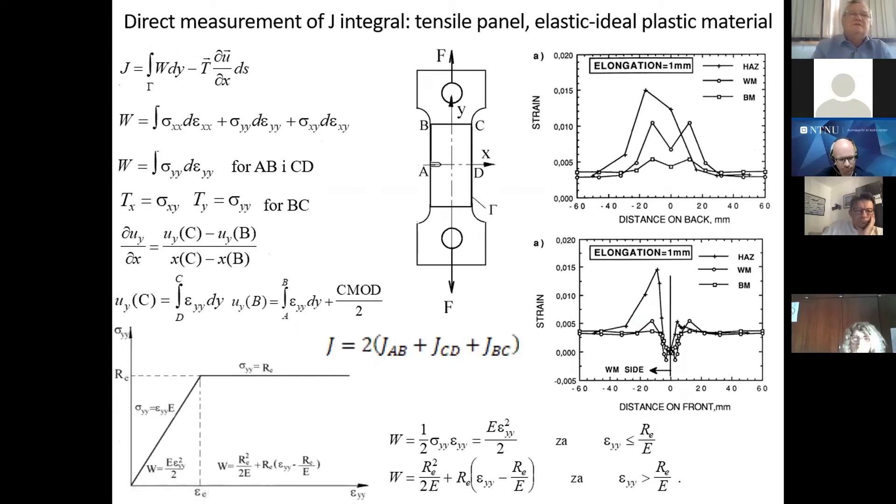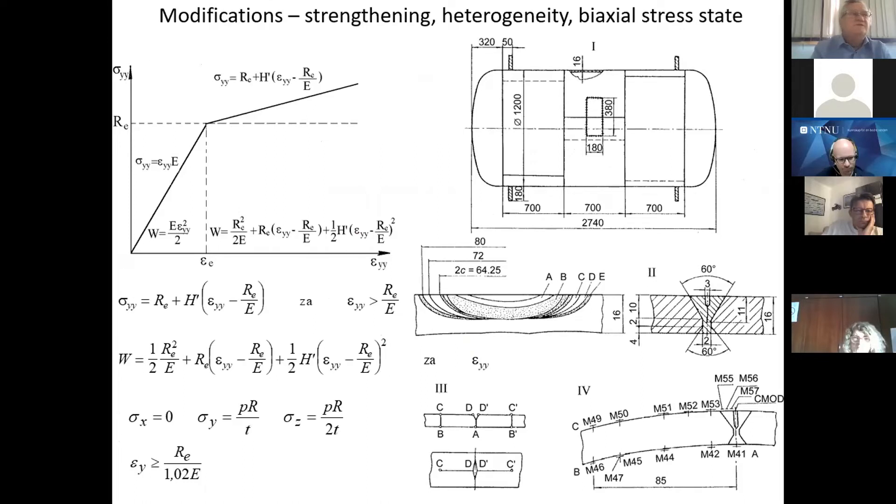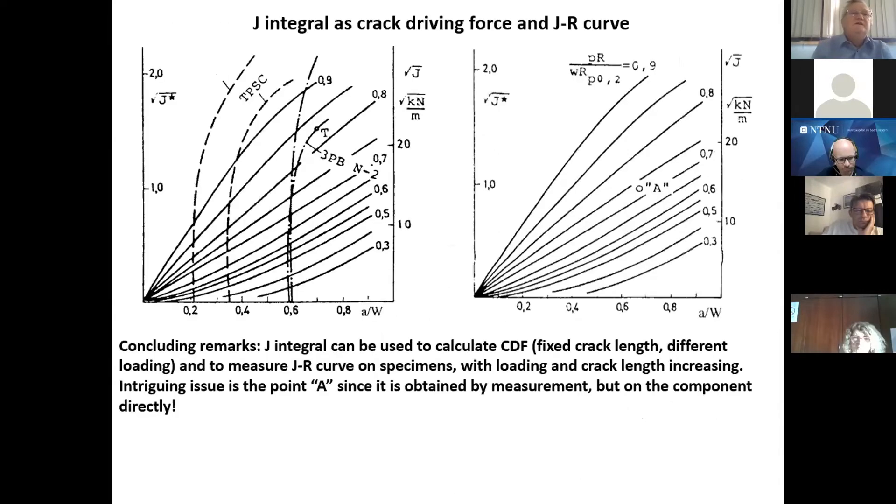There is a lot of instrumentation on tensile panels. It is a relatively simple task as compared to the pressure vessels. In that case, we had to take out a patch and then re-weld it. And that was with the purpose to instrument pressure vessels with the strain gauges and to follow strains as they develop during pressurizing. Now, here, some other aspects were also taken into account biaxial stress state and curvature, but none of it produced much discrepancies in theoretical sense. So from practical point of view, we were able to apply J-integral as crack driving force.